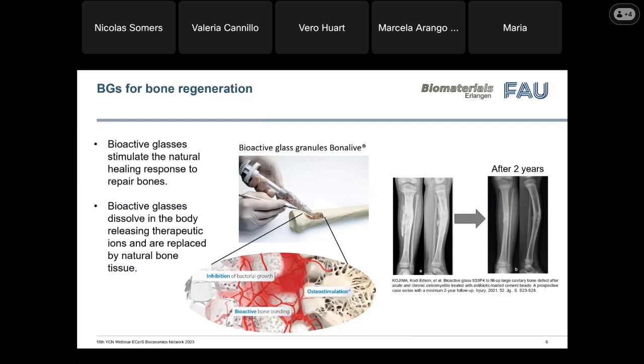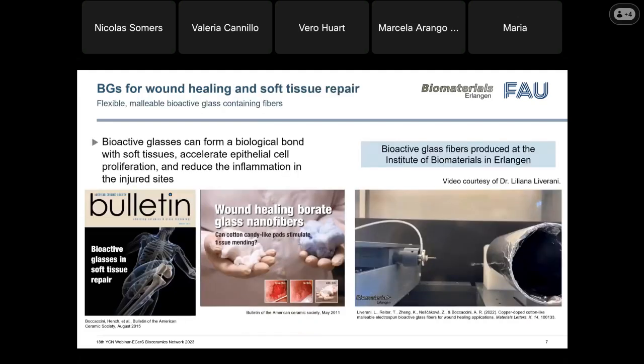On the right, we can see a case study in which a defect caused by a very chronic bone infection was filled with bioactive glasses, and then after 2 years, we can see a successful recovery with almost no particles left.